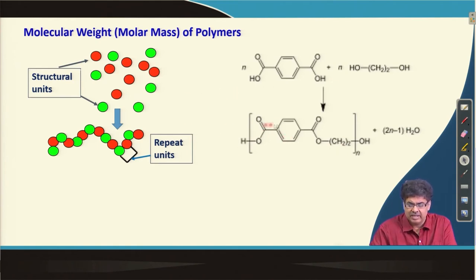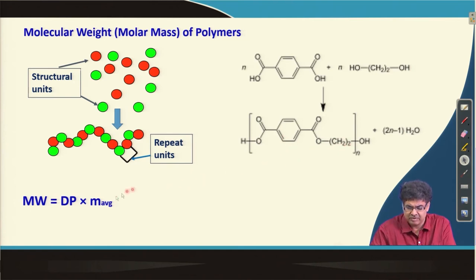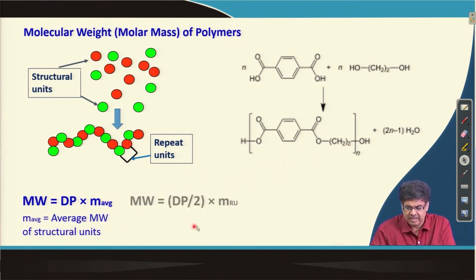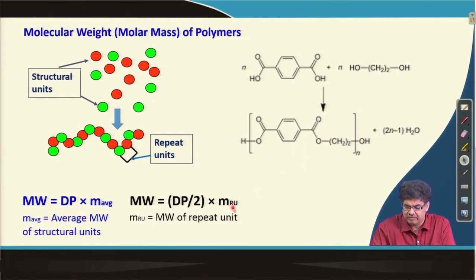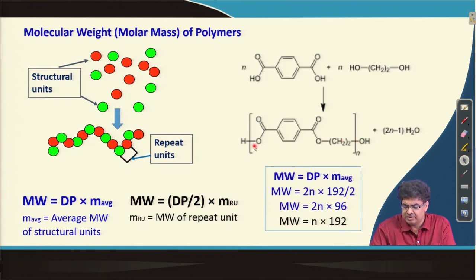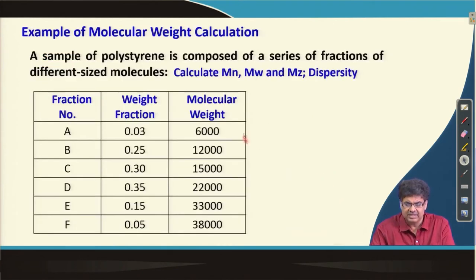For a condensation-type polymer, molecular weight is given by D_P multiplied by the average molecular weight of the structure unit, or half the degree of polymerization multiplied by the molecular weight of the repeat unit. In this particular example, the repeat unit molecular weight is 192, so molecular weight equals D_P times 96, which equals n times 192, where D_P equals twice n.